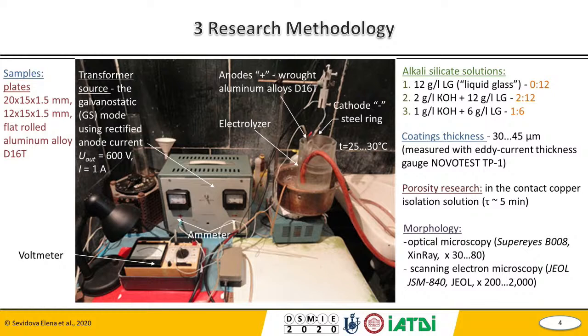And our coating thickness was measured with an eddy current thickness gauge. The results are from 30 to 45 micrometers. And the most important for us was the indication of how we can see porosity. First of all, our through porosity, and for this purpose we have used a contact copper insulation solution. So each sample after formation of PEO coatings was immersed in this solution, and after different time and drying process, our results can be seen on the next slides.